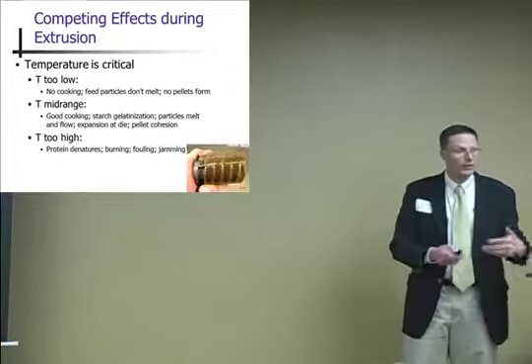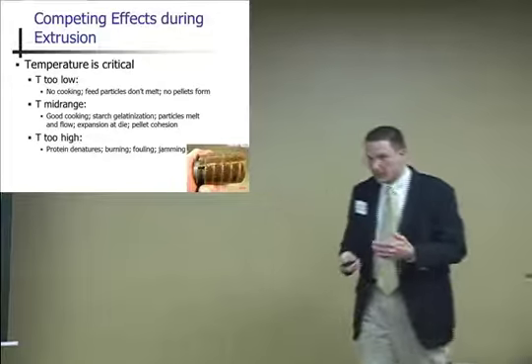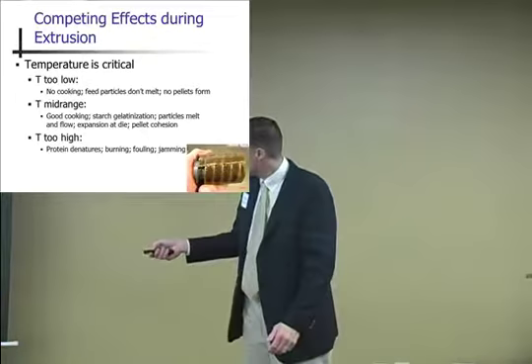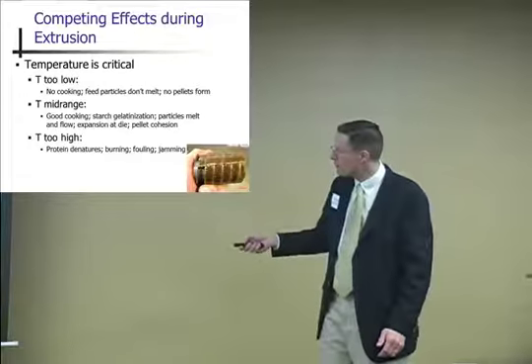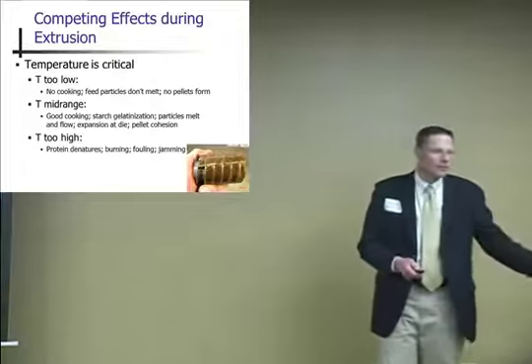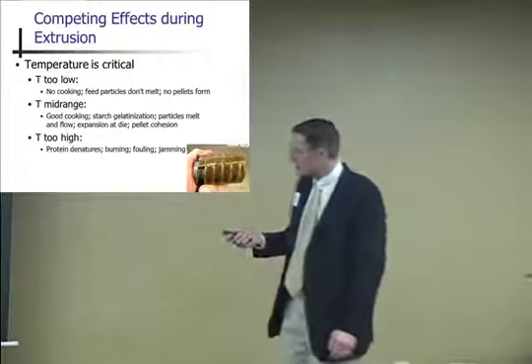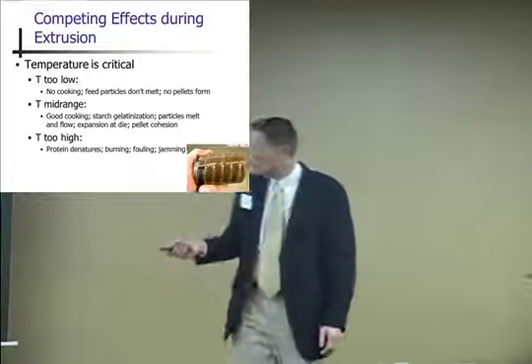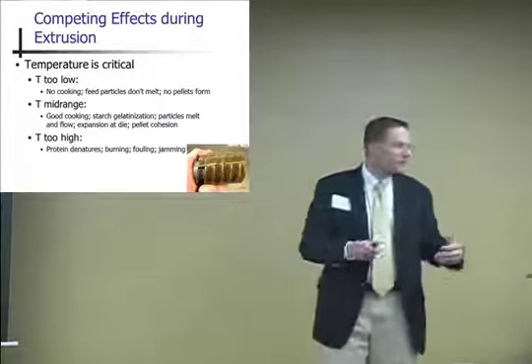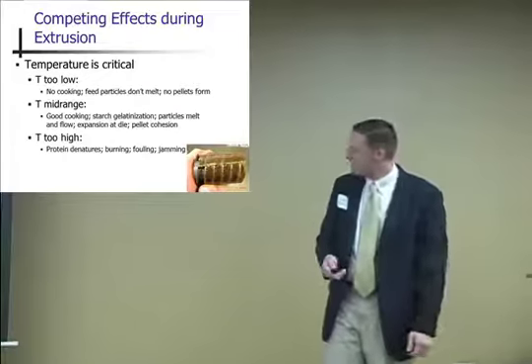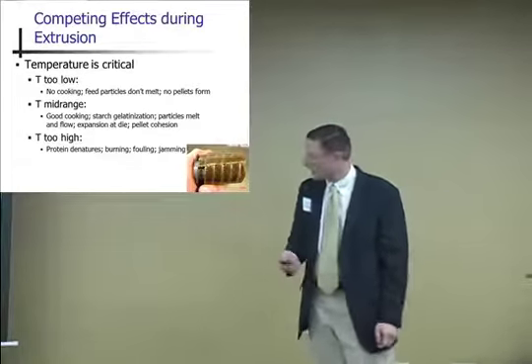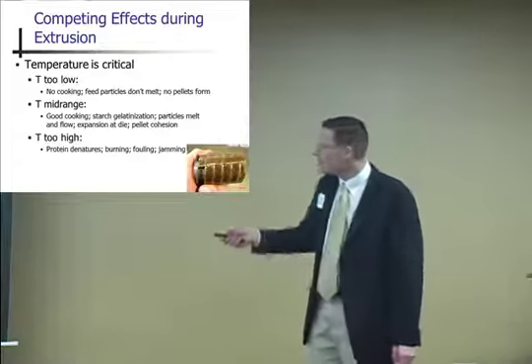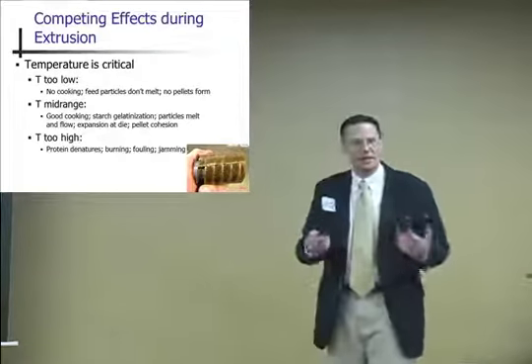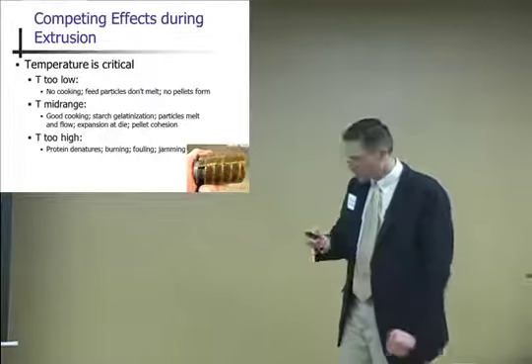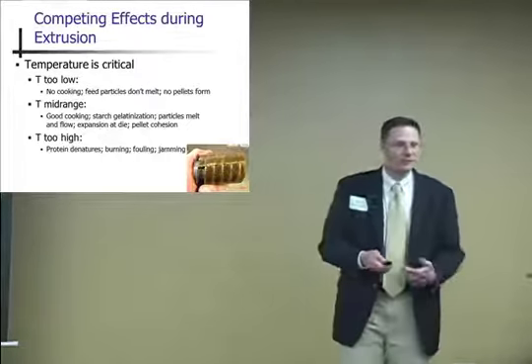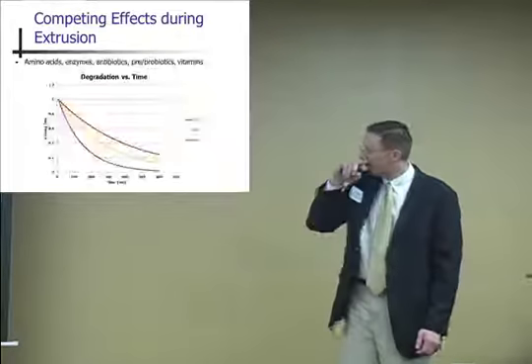So if it's too low, you're not going to cook your product. If it's too high, you're going to denature your proteins, make them indigestible, or you're going to make glass. So this is a biological form of glass. It's the proteins which have been denatured, and I tell you, the folks that I was working with were not really very happy because we had to pull that extruder apart bolt by bolt, and it took about 6 hours to take that extruder apart and clean it out. You don't want to make glass. You want to be somewhere in the middle. You gelatinize your starch, you have good expansion, you have good particle melting, and you have good pellet cohesion. So another thing to think about.